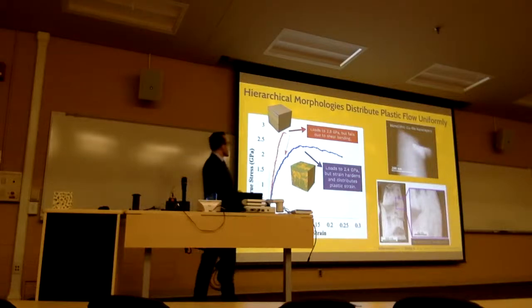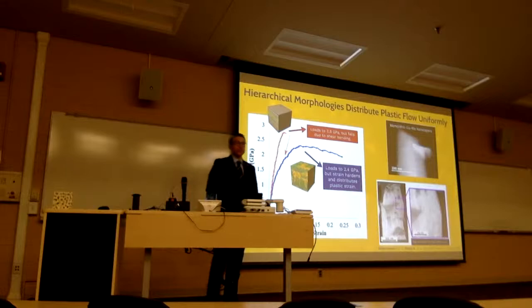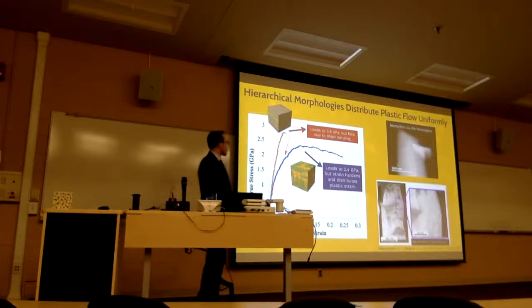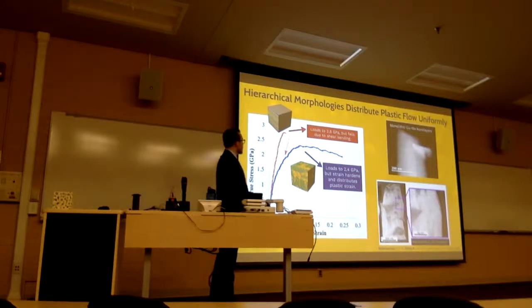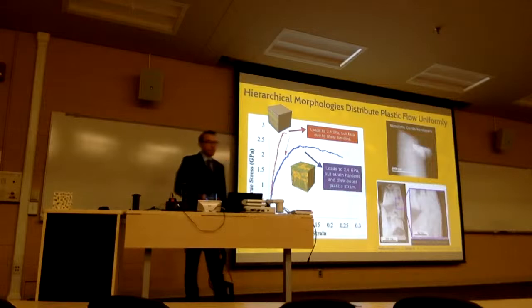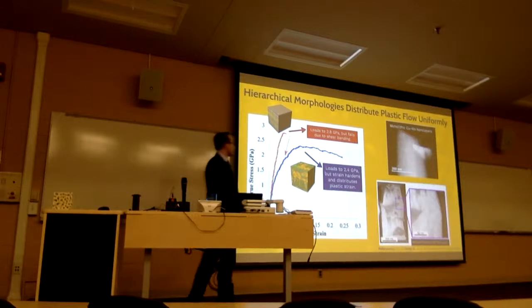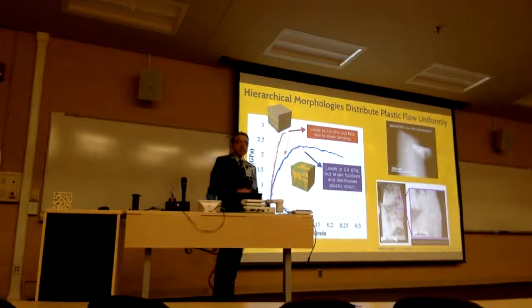Very similarly. We've actually compared the multi-layer design to a hierarchical-like morphology. In this case, the sample deposited at 400 degrees C. And we saw that the sample in the multi-layer copper moly system actually loaded to 2.8 gigapascals, but failed suddenly due to shear banding in the material. You can see that using this TEM image of the sample here.